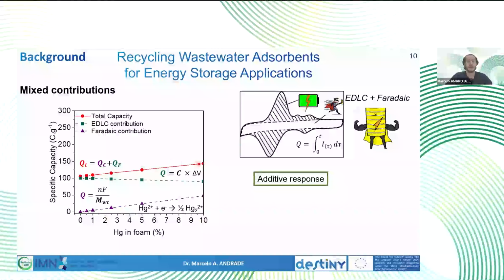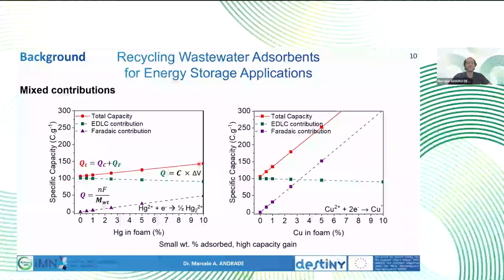So the more metal you have in your system, the more capacity it is expected to bring to this adsorbent. And as I said, the capacity is basically related to the molecular weight. So if you have lighter atoms or a higher oxidation state with more electron exchange, you'll have a higher total increase in expected capacity. So in theory, everything should work nicely, and we would extract energy from the entrapped cations inside these spent adsorbents.